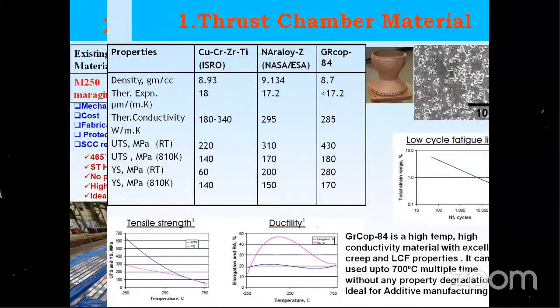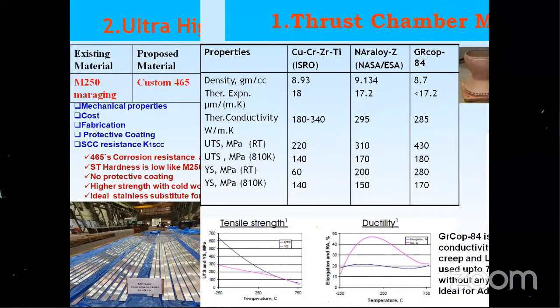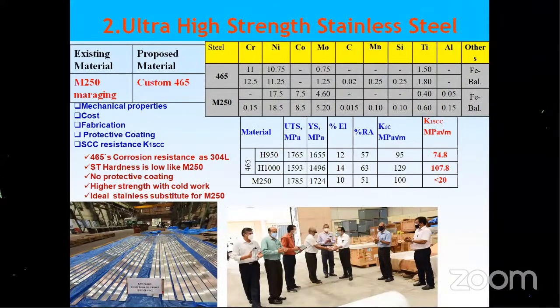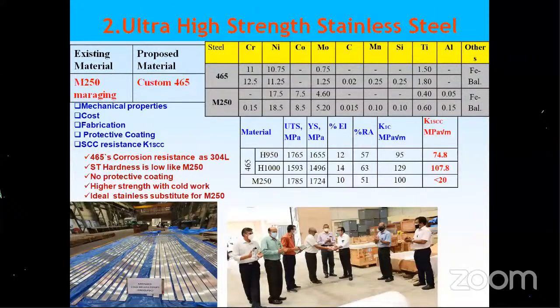Then this is another high strength material, which was developed by me. It is a substitute to maraging steel, which is actually stainless steel, containing stainless steel properties with all the maraging steel behavior. The composition is like this. It contains chromium and nickel. And with maraging steel, one of the issues is that when you make a fastener or any sharp notched application, it fails because of the SCC issue. And the KISCC is so low, it's less than 20, whereas this material has a very high KISCC, which I already made and supplied, and we formed strips for making into the Marman band of our active satellite separation system.